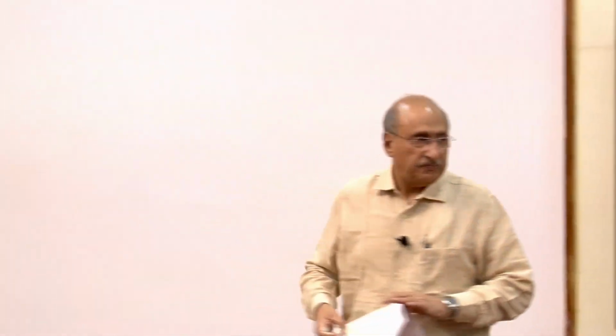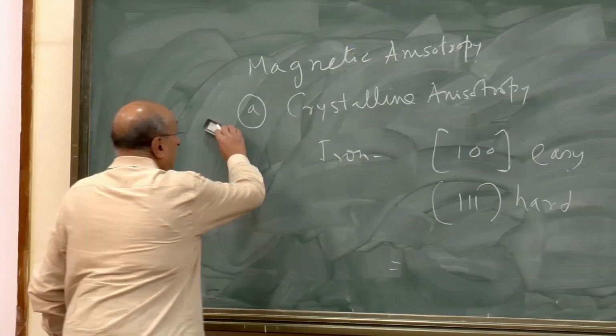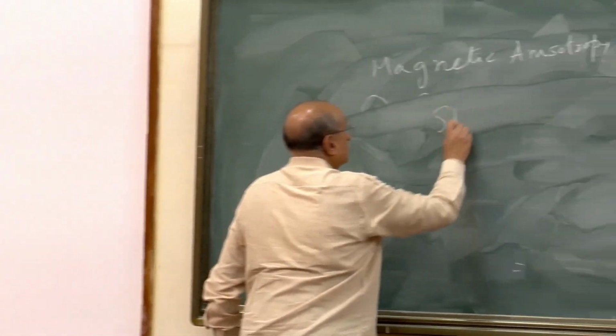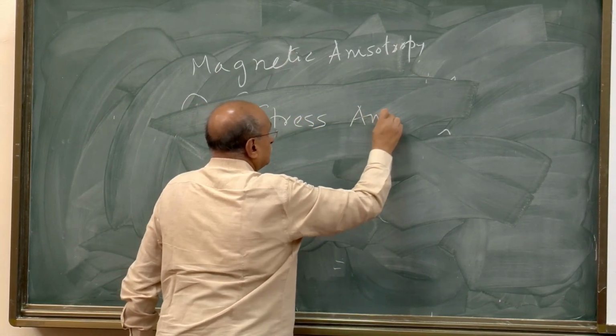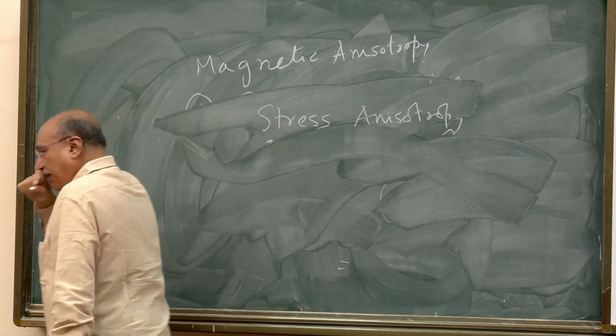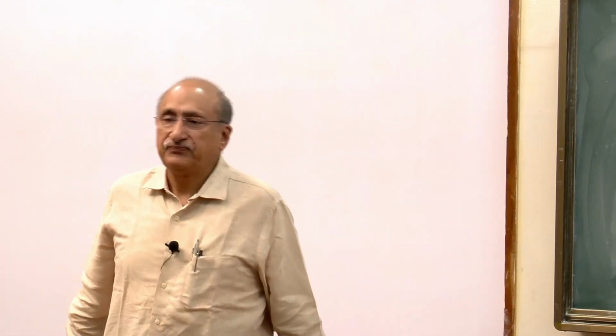Another is what we call stress anisotropy, also very common and very useful. There are many materials in which this has been used favorably to make devices. There are many materials which are magnetostrictive, where you apply pressure and then the anisotropy direction changes. Especially when you are talking of ultra thin films, it's easy to stress them by putting them on a substrate which has a slightly different lattice constant. There are ways of doing it. And people have done it by implanting ions inside a lattice, so they expand the lattice, and because of that the anisotropy changes. They are essentially stress induced anisotropy.